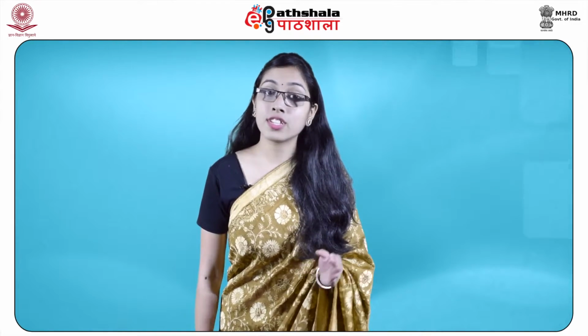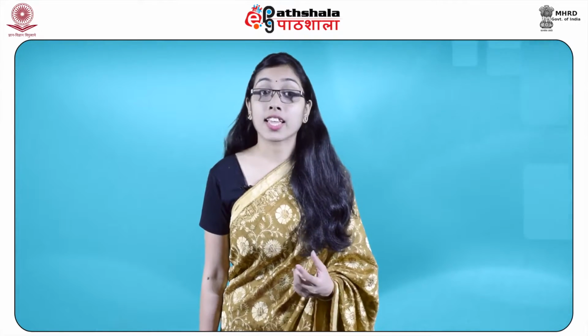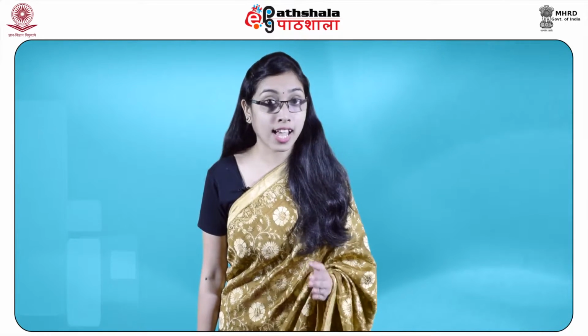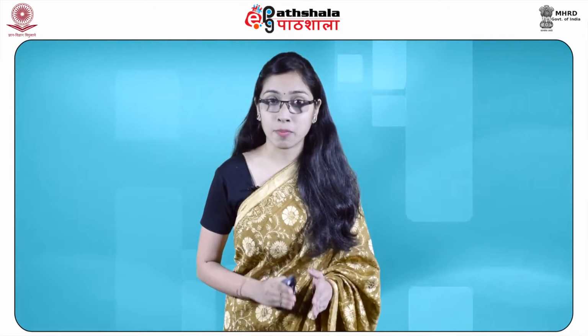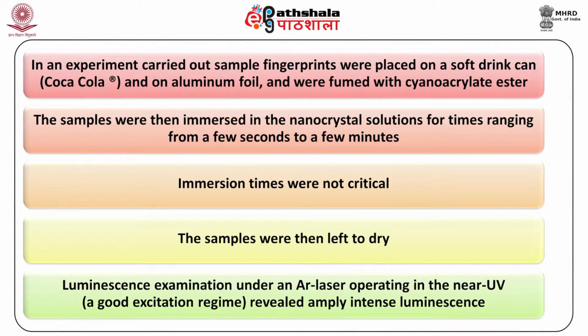Because staining with fluorescent dyes after cyanoacrylate ester fuming is a very successful fingerprint detection methodology, dioctyl sulfosuccinate-capped CdS nanocrystals, that is cadmium sulfide nanocrystals dissolved in heptane or hexane, can be employed in this manner. In an experiment, sample fingerprints were placed on a soft drink can and on aluminium foil, which were fumed with cyanoacrylate ester. The samples were then immersed in the nanocrystal solution for times ranging from a few seconds to a few minutes. The immersion times were not critical. The samples were then left to dry.